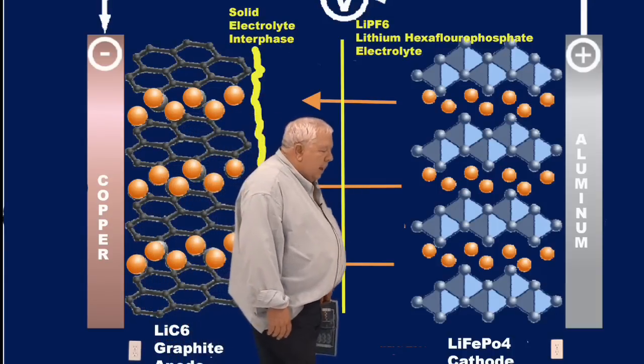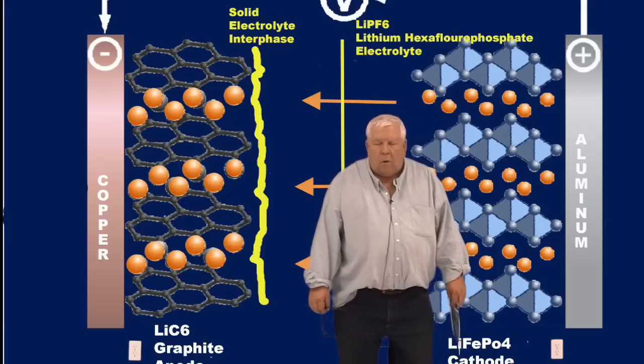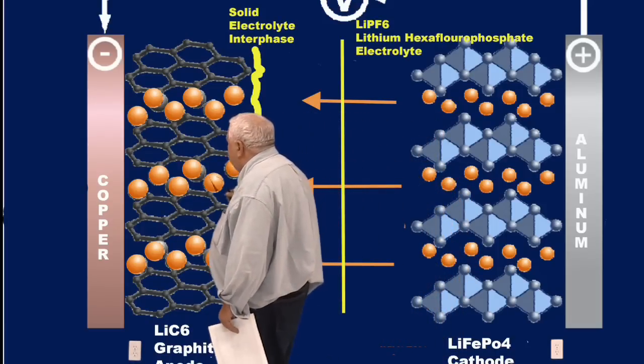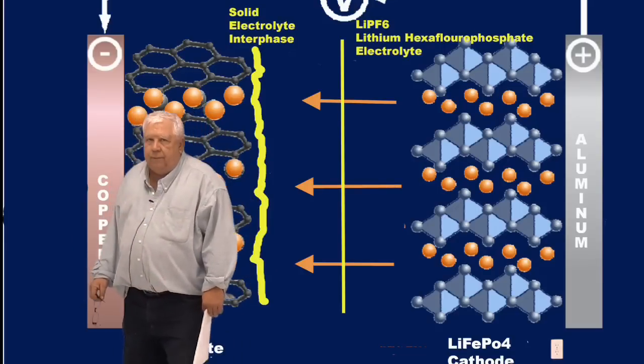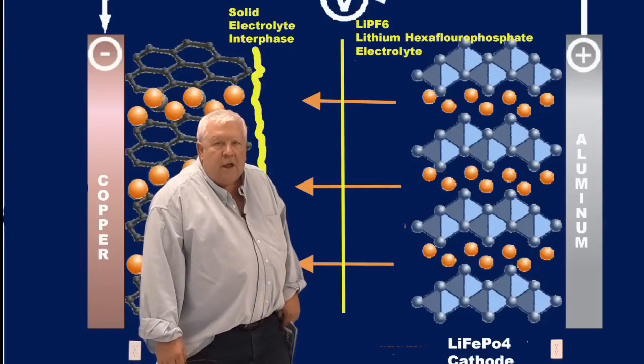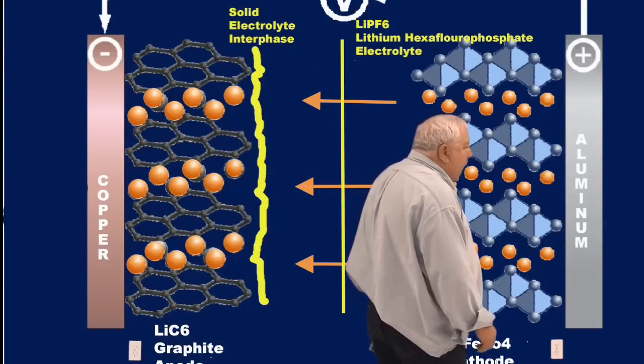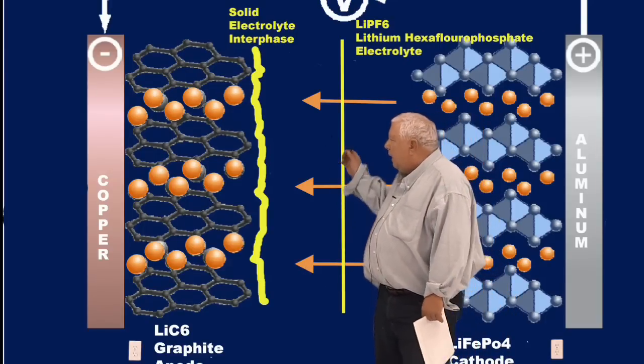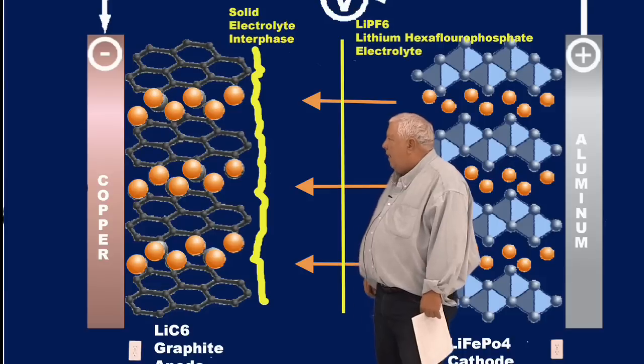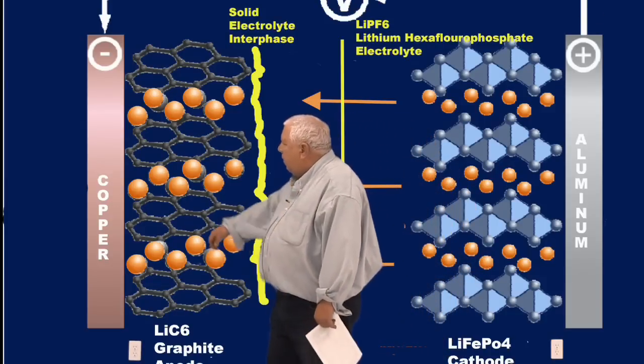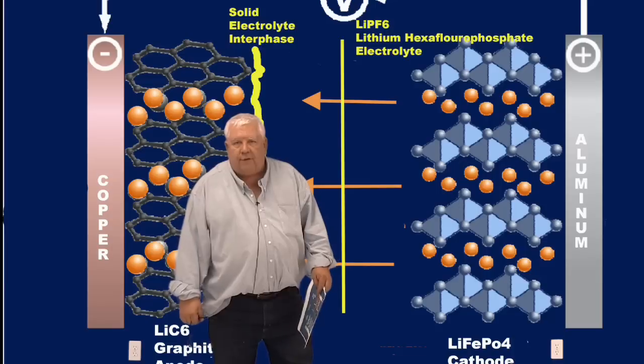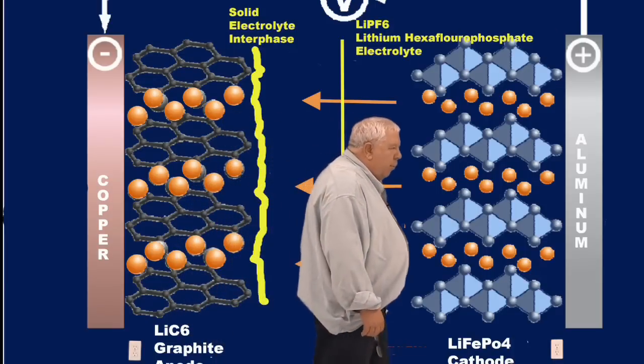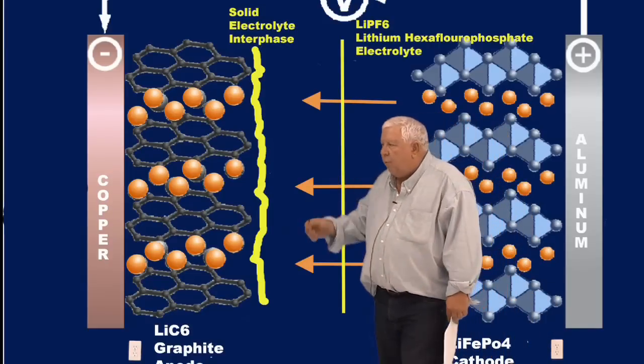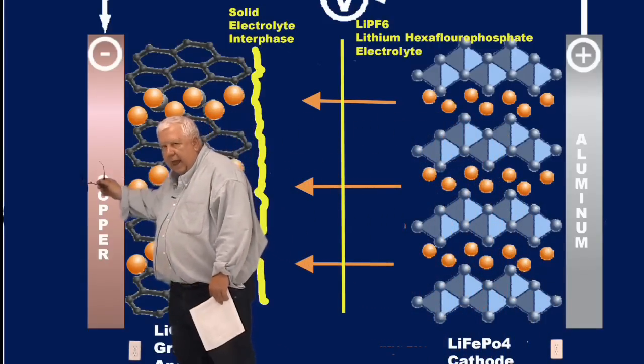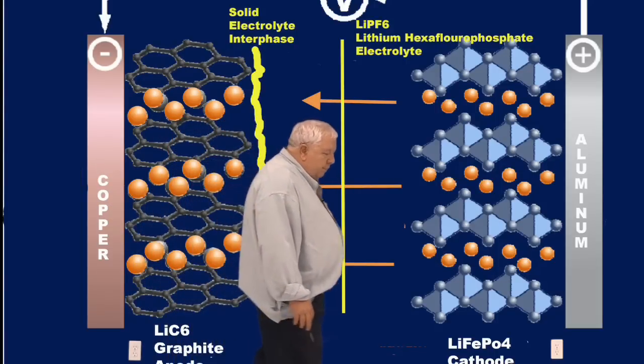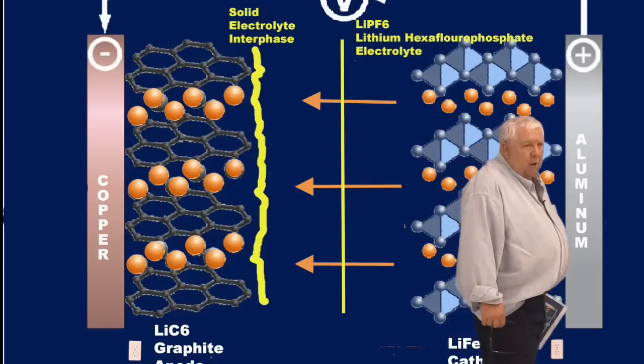And we can get very quickly into a thermal runaway situation that not only shorts the cell and causes high currents, but blows up our SEI layer, allowing all our lithium ions that we've stored there to suddenly begin to react with the solvents in our electrolyte, not in an orderly fashion as in charging, and not in an orderly fashion such as discharging, but suddenly our SEI layer is breaking down and we've got an inrush of solvents into the intercalated lithium, and that goes into thermal runaway. And so normally a thermal runaway situation starts in the anode, not the cathode. And that's where the temperature starts to rise, and away we go.